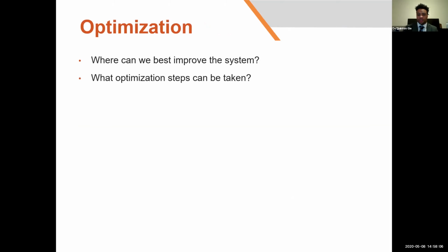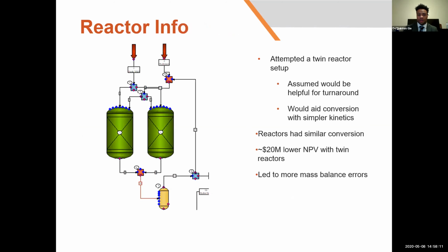So during our optimization, we're going to talk about where we thought we could best improve the system and what steps we took in order to improve it. From a topological standpoint, we attempted to run a twin reactor setup. We assumed 2 reactors would be cheaper than 1 large one, and that it would be helpful for turnaround and would help us develop simpler kinetics. It didn't really have much of an effect on kinetics, and the reactors had similar conversion after all. But having 2 reactors actually resulted in a $20 million lower NPV than having 1, as well as leading to more mass balance errors within our ChemCAD simulation. So we switched back to the 1 large reactor.